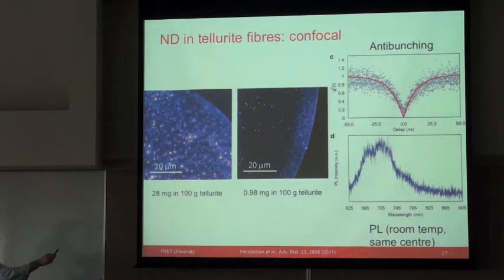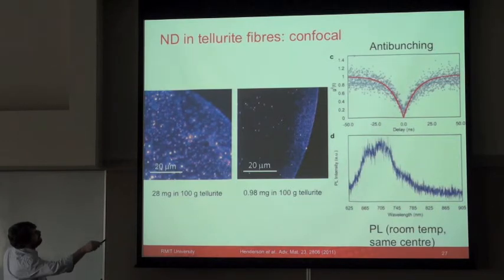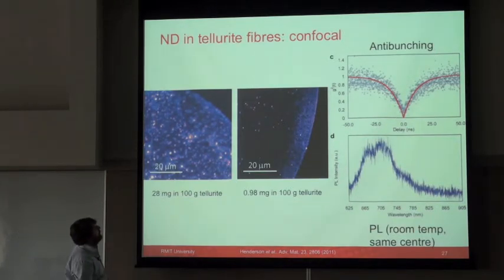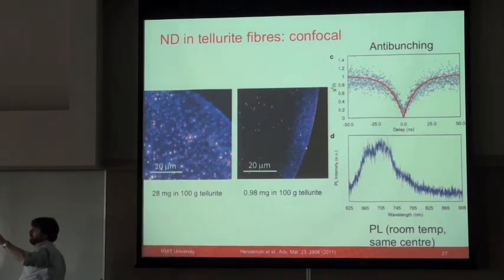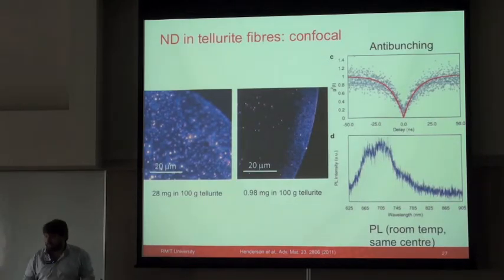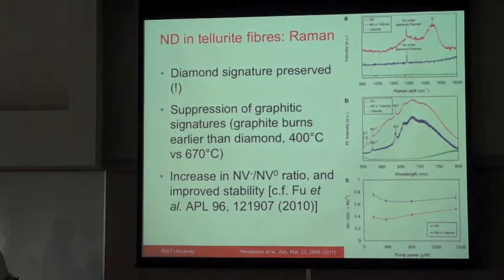This picture here is now a confocal image of the tellurite. Most of these bright spots here are in fact fluorescent nanodiamonds, which we can confirm by looking at the room temperature photoluminescence, and we can also observe very clear anti-bunching. So what this tells us is that we can put nanodiamond into tellurite, and we can extrude it into an optical fibre shape, and the nanodiamond properties are preserved. Not only are they preserved, they're actually better, and we believe some of this is due to the fact that the graphitic shells on our nanodiamonds are being burnt away. Graphite burns at around 400 versus the 670 degrees of the diamond, so we think we're getting some preferential etching and annealing.